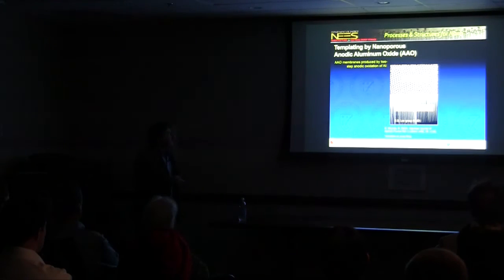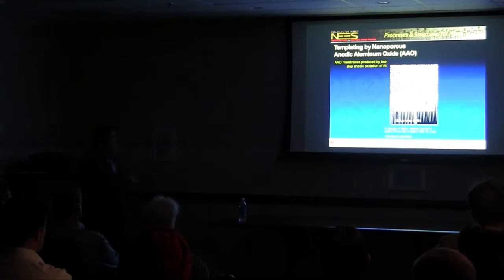You want to make other kinds of structures with multi-layers, and so here's another approach to doing that. Here I show some nanopores, these holes in these gray areas. They've been filled by multiple layers of materials. Some could be current collectors to just move electrons back and forth. Some would be active materials to hold lithium ions or sodium ions as storage material. Or you can take this kind of structure and essentially remove this part, turn it upside down, and get another kind of structure. So we call these nanotube structures, nanowire structures. The blue stuff is exposed to the electrolyte, so that can be useful in a battery or a capacitor kind of configuration.